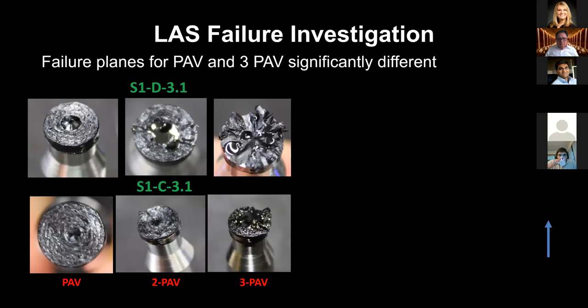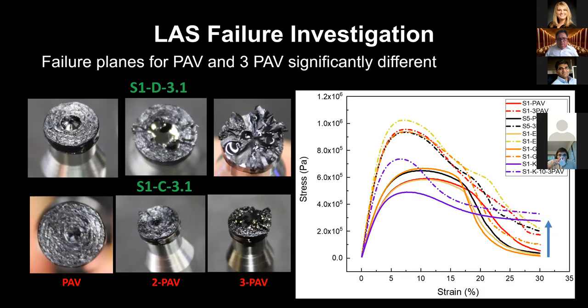Challenges were faced when running the linear amplitude sweep and interpreting the data, as the post-test failure planes were challenging. There was a mixed effect with the accumulated energy until failure. That is, the stiffness plays a role in shortening the test because more energy per cycle is applied to the samples and results in an unreliable trend and poor data post-peak. The stress versus strain curves generated demonstrated distinct trends as the material ages. The researchers felt that the curves could be used to characterize the performance of the modified binders if the data was analyzed in a unique manner and avoided those post-peak issues.